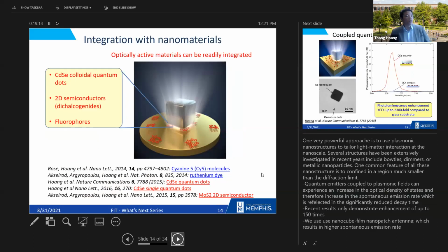And we are going to make use of that field enhancement, as I'll show on the next slide. What you're seeing here is the same structure again, but we are going to put some active materials into that gap. Like I said before, the gap is only about 10 nanometers or so. So if you want to put something into that gap, the material has to be really small. And that's why we have to use nanomaterials. In this case, we can use quantum dots, cadmium selenide quantum dots, or we can put a 2D material into that gap, or we can put some dye molecules into that gap. Okay, so that's just what we did.